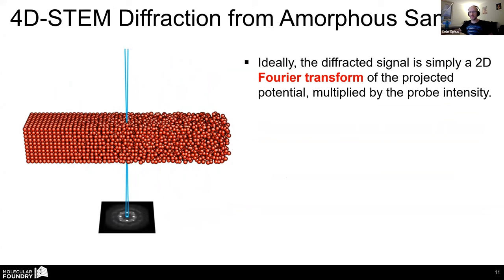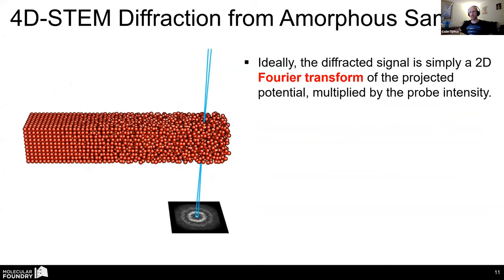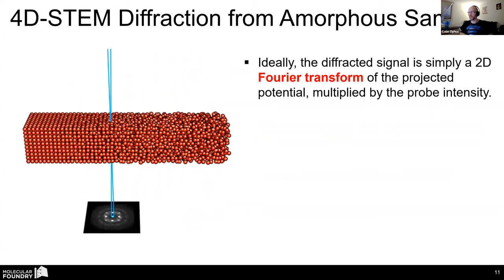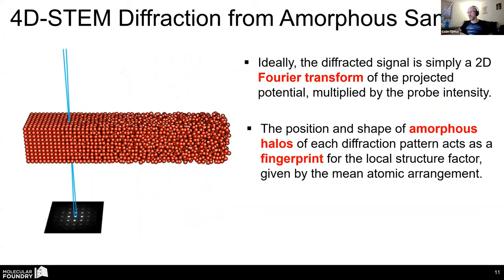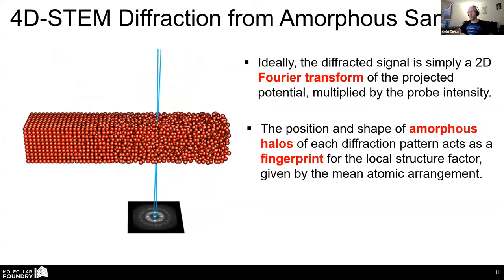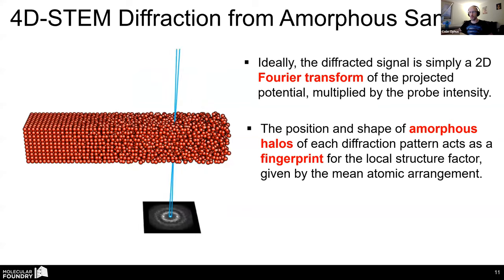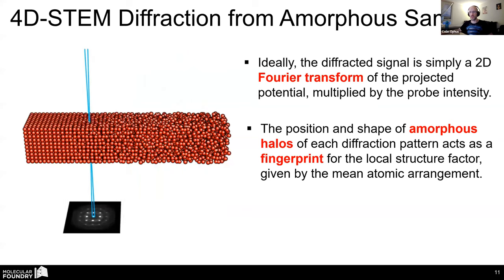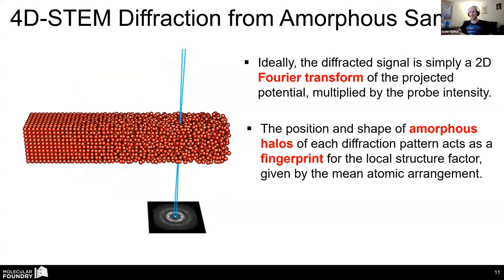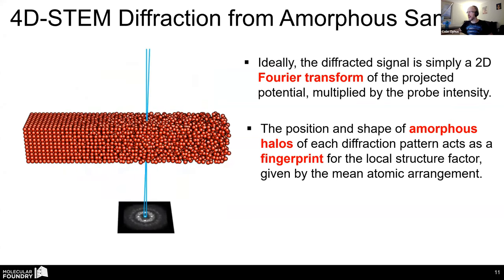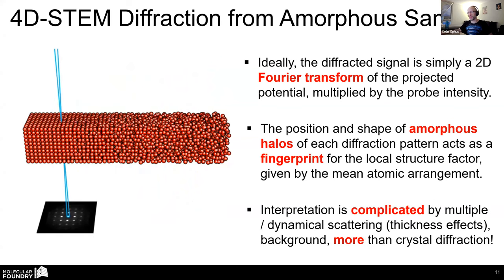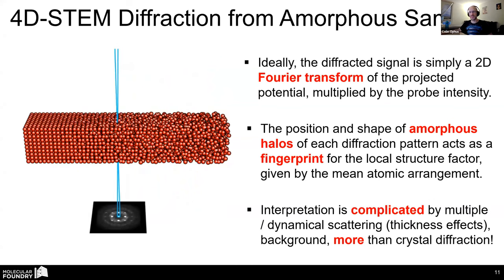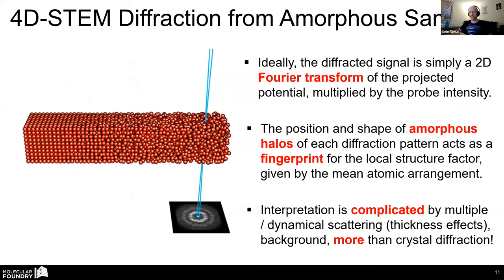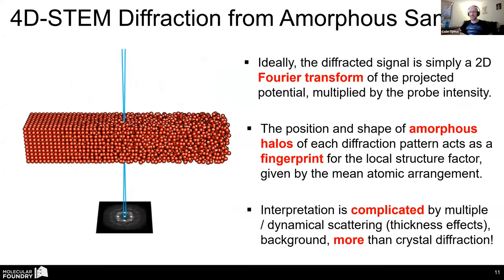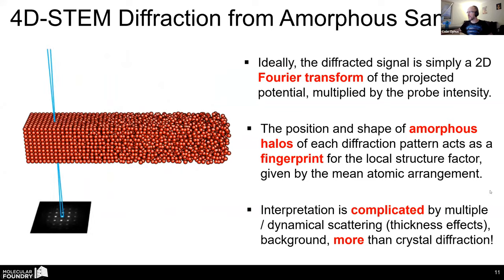We're measuring a diffraction pattern where the illuminated volume is the projected area of the probe on the sample surface. And similar to the crystal materials, what we call these amorphous halos are a unique fingerprint for the local structure of the material. This can be used for things like short range order mapping, medium range order mapping, or even strain mapping, as I'll show in this talk. I mentioned that multiple scattering complicates crystal diffraction. It's perhaps even more of a detriment in amorphous materials. These are very, very challenging to study.